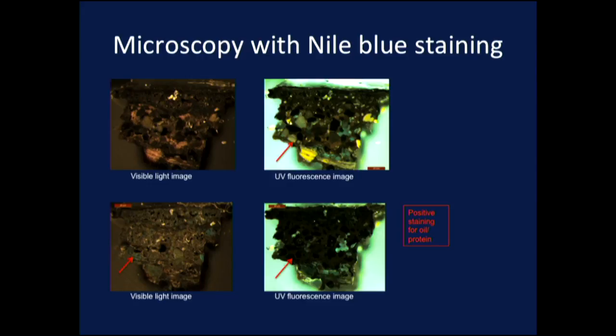But here, the bone in particular is staining blue and black in visible light, so you have these particles that are all bone that before the stain, you have no blue, and then after the stain, it's localized in these bone particles, and the stain turns white bone to black. It shows that there is protein and/or lipids in the bone fragments in these samples. So this does say that some of the proteomics that was done did at least include some proteins from the bone, because we weren't totally sure if the protein that was analyzed could be coming from the bone or from the lacquer.